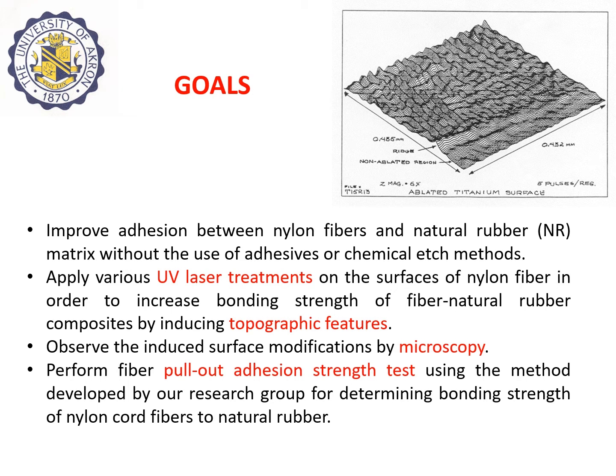With these types of topographic features, we are talking about features similar to the picture that I show on the upper right, which depicts an excimer laser irradiated titanium surface that we worked on in the past. You can see here that even titanium can be irradiated and melted on the surface to obtain such topographic wavy patterns. We then wanted to observe the induced surface modifications by microscopy and perform pull-out adhesion strength tests using the method developed by our research group for determining bonding strength of nylon cord fibers to natural rubber.